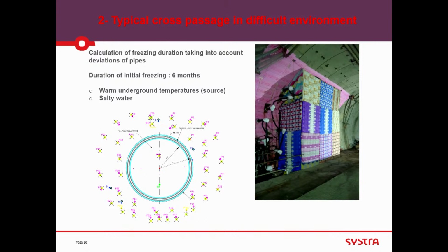And it was open for months. So we were obliged to decrease the allowable stress to 2 MPa in the frozen body, and to have a 3 meter thick frozen annulus. So we needed, in fact, 2 lines of drilling to get this 3 meter thick annulus.